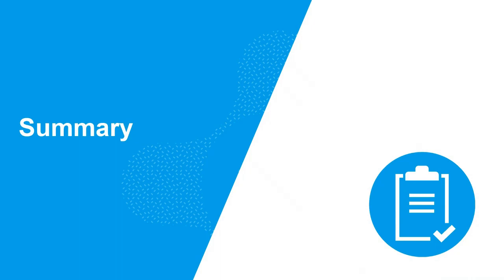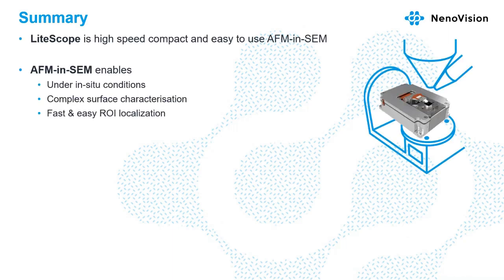I'd like to summarize what we were talking about today. We were talking about LiteScope, that it's a high-speed, compact, and easy to use AFM-in-SEM. It's quite fast also to integrate the LiteScope into the chamber. AFM-in-SEM solution enables us to measure under in-situ conditions in the same place and at the same time. We are able to measure complexly several different signals, both from SEM and AFM, such as the chemical composition of the sample, material contrast, and the electrical, mechanical, and magnetic properties. And also, it's quite fast and easy to localize the area of interest using these devices together.